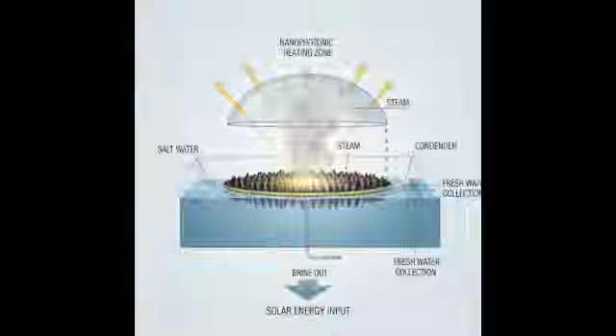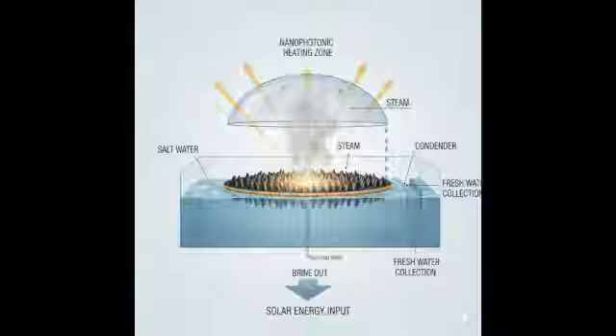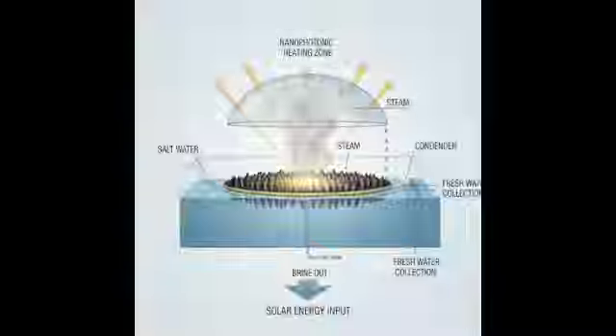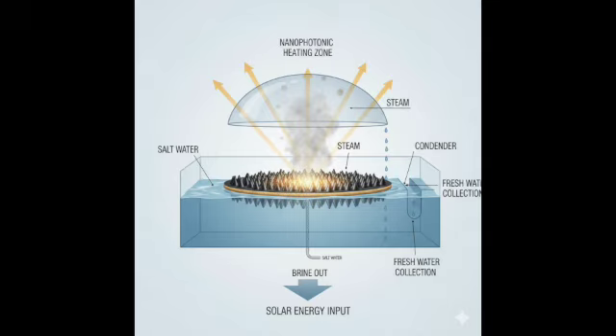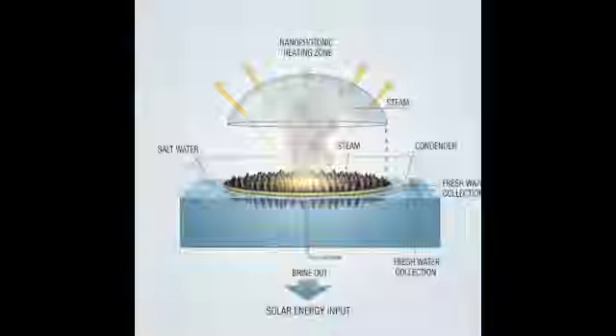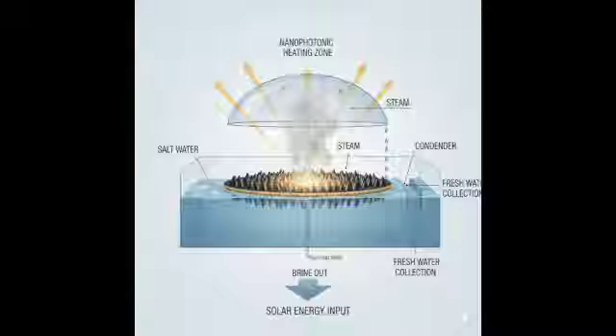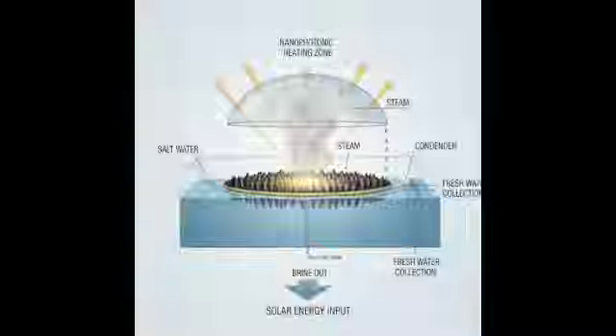Okay, the technical and environmental case seems strong, but ultimately adoption comes down to techno-economics. How does SPMD stack up financially? Let's start with energy consumption metrics. This is where we need to be realistic, especially comparing to the dominant technology, reverse osmosis, RO. MD, including CMD and SPMD, when considering total energy input, thermal and electrical, typically requires somewhere in the range of 10 to 40 kilowatt-hours per cubic meter. How does that compare? Well, older thermal methods like multi-stage flash, MSF, are much higher, at 50 to 80 kilowatt-hours per cubic meter. But modern seawater RO, SWRO, is incredibly optimized, operating down at 3 to 5 kilowatt-hours per cubic meter.